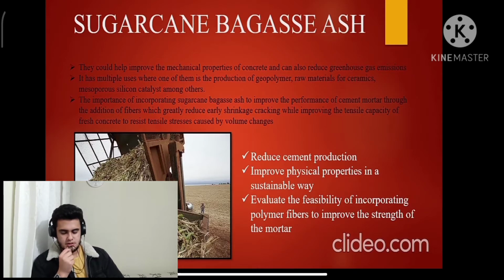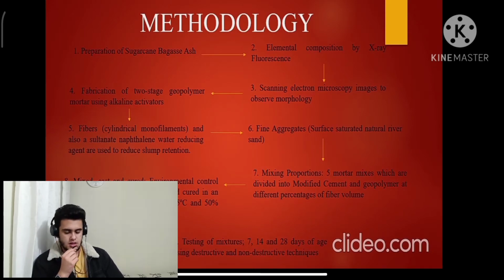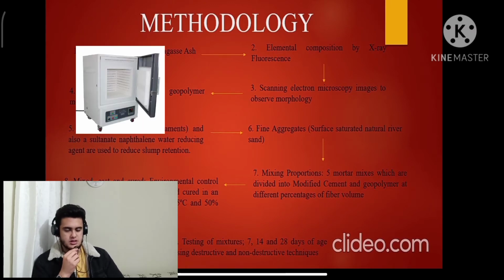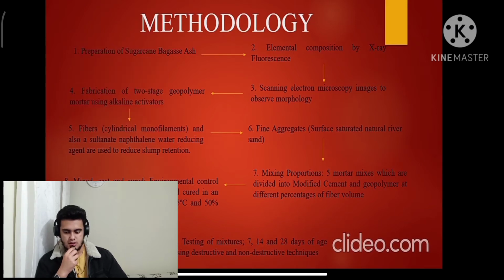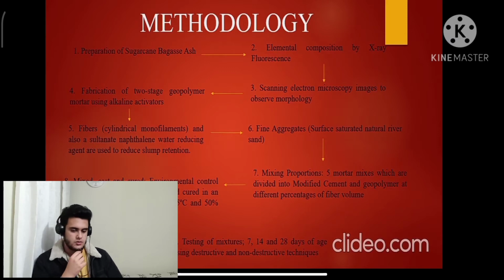in a sustainable way. As a methodology, we have 7 steps. The first is taking the sample, which is heat treated in a muffle furnace for 2 hours at 900 degrees centigrade. Then it is left to dry in the open air and is taken to a ceramic mortar to be crushed until we reach the same fineness as cement.